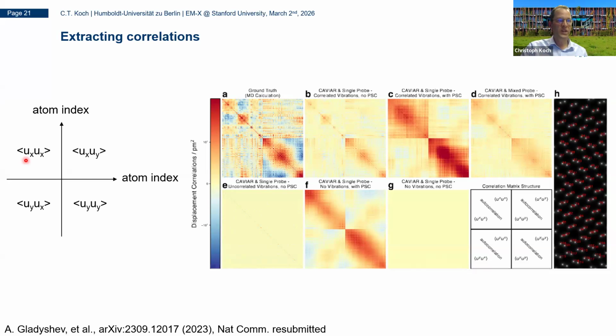modes that we recover. And this is the original object. This basically are the correlations from the MD simulations. And we can see here, these are the correlations when we do the reconstruction using this multi-object reconstruction with partial spatial coherence included. And you can see here, the amplitude actually is lower than what we expect from the MD model, but the correlations actually are quite well reproduced.